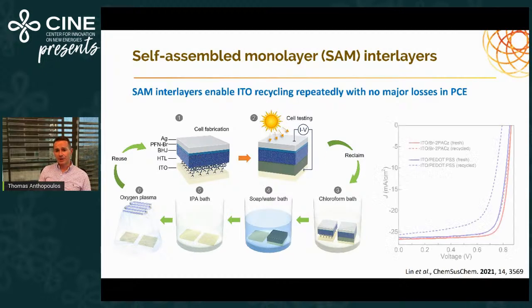And essentially what we discover is that when we're using SAMs instead of PSS, we can actually do this several times without a drop in the overall efficiency between reclaim and reuse steps. While in the case of PEDOT, the device efficiency drops dramatically after only 3 cycles of reclaim and reuse, without the possibility to recover the original performance. This is clearly not the case with the SAMs, because the performance of the SAMs actually remains the same. So essentially, that's an interesting finding we did not expect.